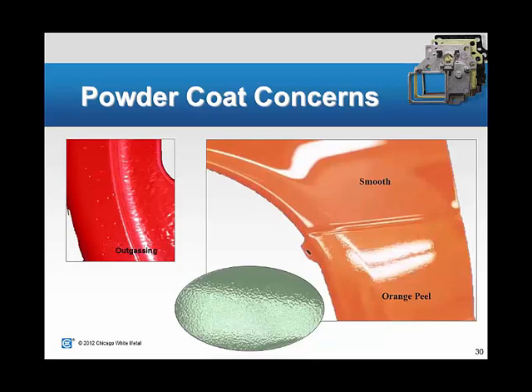Another thing that will help alleviate the outgassing is preheating the parts at the powder coater prior to being processed. That will typically control the amount of outgassing that occurs, and again, something to talk over with your die caster about.